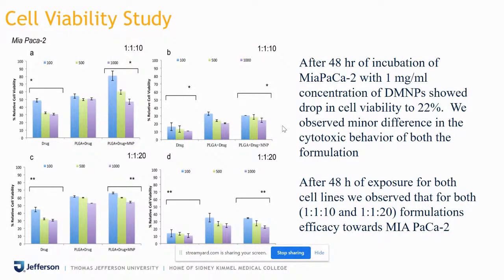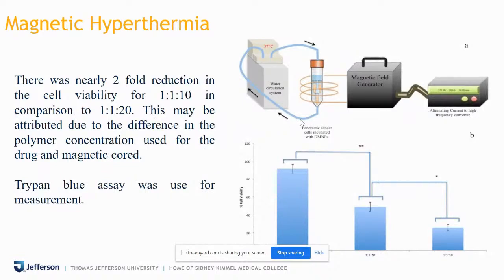So we did the cell viability assays with the 17-AAG. We did it with two cell lines, MIA PaCa-2 and L929. I've not shown the data for L929 here; I just wanted to focus on the MIA PaCa-2 cell line. We could see that after 48 hours of incubation, we could get sufficient cytotoxicity for killing the cancer cells using the drug PLGA MNP formulation for both formulations. Since we were getting good cytotoxicity with MIA PaCa-2 cells, we wondered whether this would also have a magnetic hyperthermia effect, because we have Fe3O4 present in it. So we went ahead with the magnetic hyperthermia.